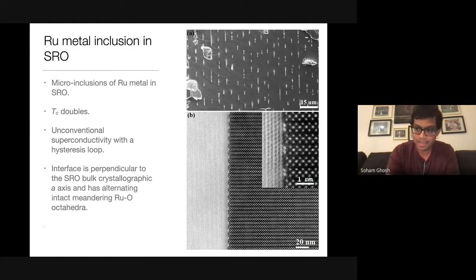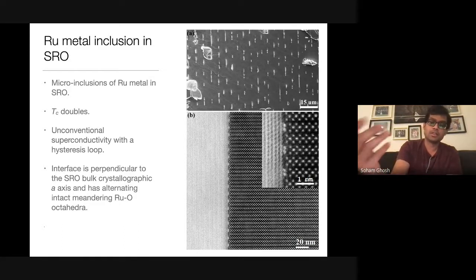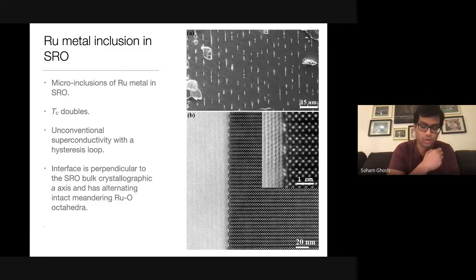Now, what are the implications of it? The implication is that strontium ruthenate is a superconductor. It's actually an unconventional superconductor, but you don't have to worry about what unconventional superconductivity is. Just know that it is a superconductor. But if you have these metals inside this oxide, then you have a superconductivity which is, instead of 1.5 Kelvin, it becomes 3 Kelvin. So it's a doubling of superconducting critical temperature, which is somewhat strange and somewhat not common. And it also has a hysteresis loop, which is also not common for superconductivity.